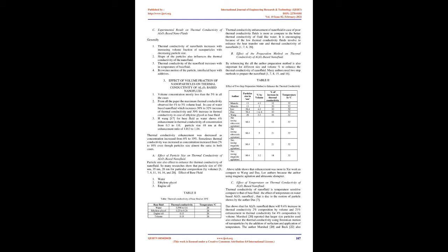Effect of volume fraction of nanoparticles on thermal conductivity of Al2O3 based nanofluid. Volume concentration is mostly less than 5% in all the cases. From all the papers, the maximum thermal conductivity was observed for 4% to 5% volume load. In case of water-based nanofluid, this shows a 30% to 32% increase in thermal conductivity, and 30% increase in thermal conductivity in case of ethylene glycol as base fluid.